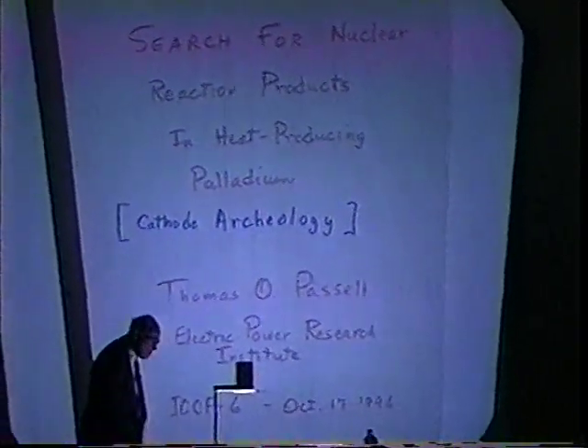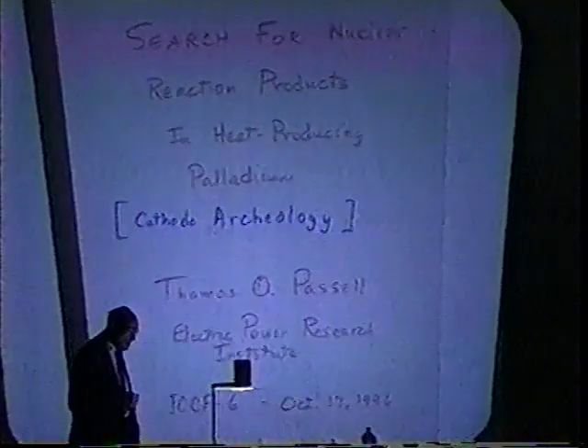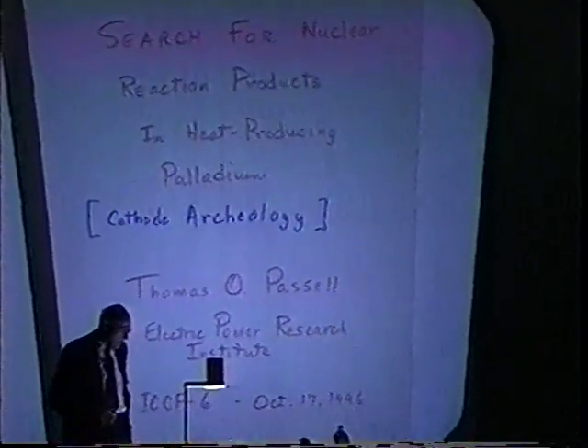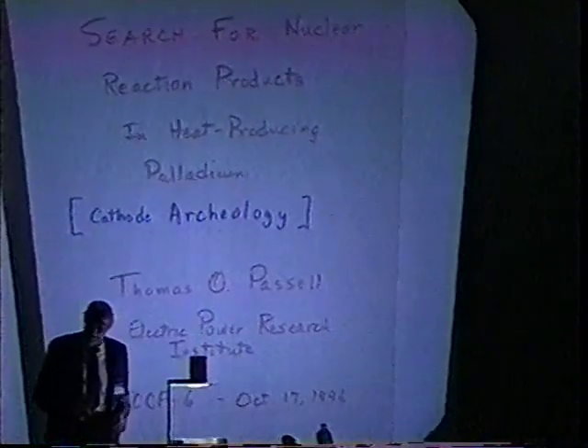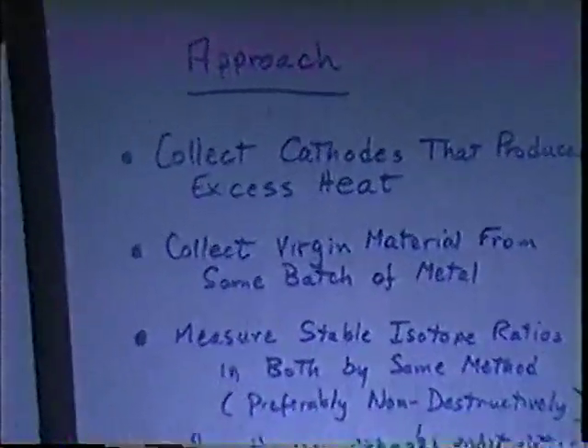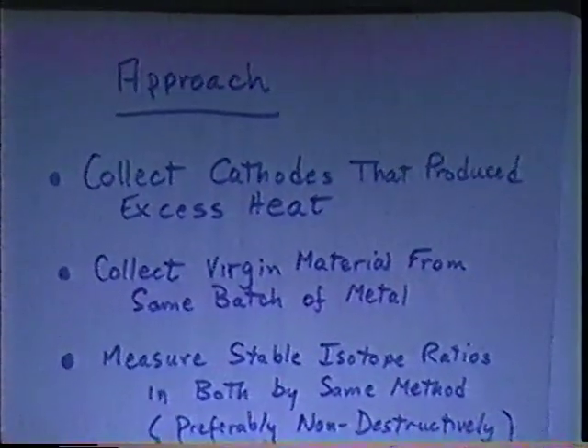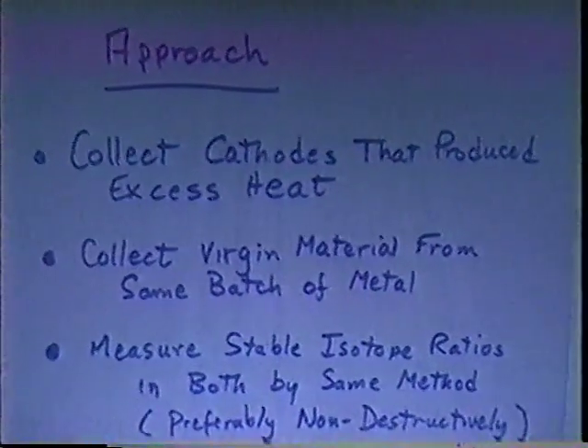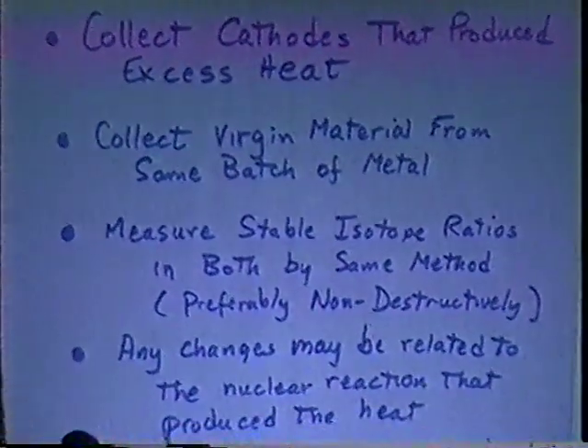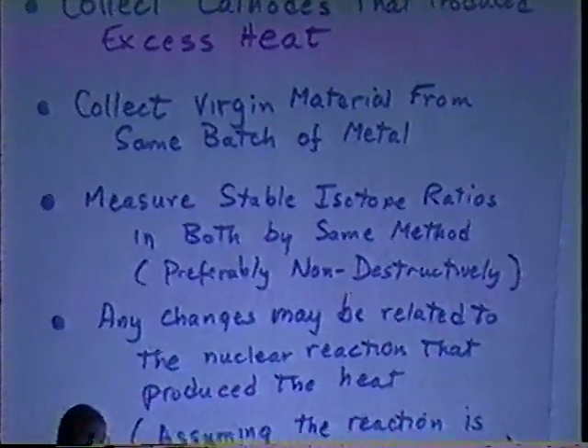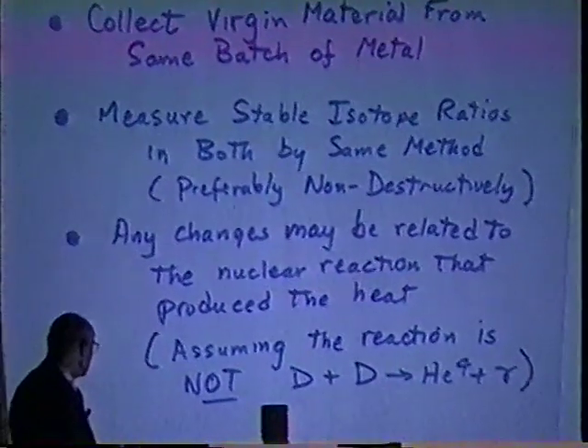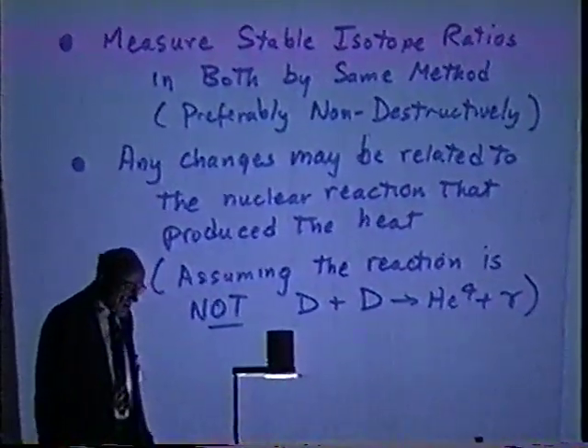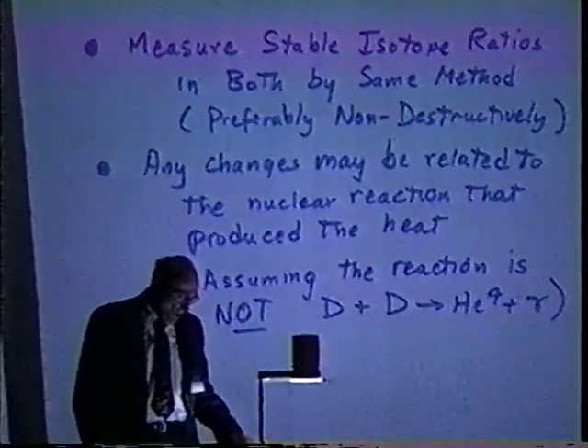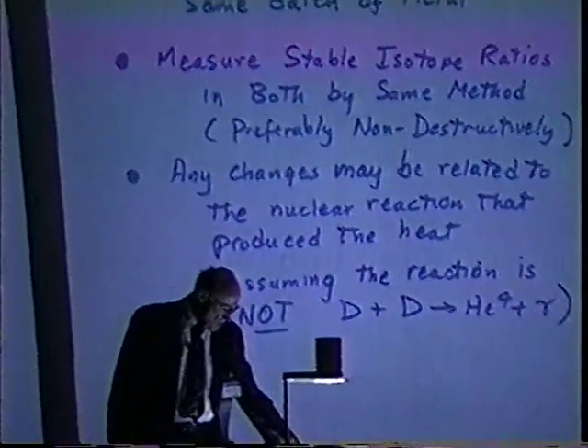Looking back at old cathodes that produced heat in various experiments to see if there was any difference in them relative to the materials out of which the cathode was made. The approach that I've taken is to collect cathodes that produce excess heat in as large a quantity as I can find, collect virgin material from the same batch of metal, and measure the stable isotope ratios in both by the same method, preferably non-destructively. Any changes may be related to the nuclear reaction that produced the heat, assuming that the reaction is not D plus D to make helium. If so, I couldn't possibly see any changes.